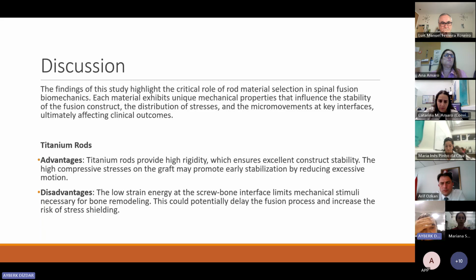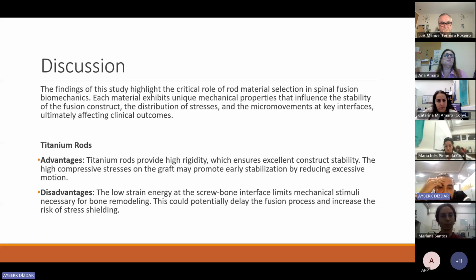Titanium rods provide high rigidity, which ensures excellent construct stability. The higher compressive stress on the graft may promote early stabilization by reducing excessive motion. Disadvantage: the low strain energy at the screw-bone interface limits the mechanical stimulation necessary for bone remodeling. This could potentially delay the fusion process and increase the risk of stress shielding.